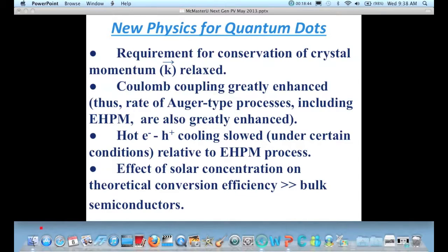And for the case of extracting them, which I won't talk about, but this is where we started looking at this, these are the so-called hot carrier solar cells. The efficiency calculated using the Shockley-Queisser approach, but assuming that the electrons don't relax or cool by phonon emission, but are extracted faster than the phonons and electrons can interact, can produce efficiencies above 65%. So you more than double the Shockley-Queisser limit with a hot electron or a hot carrier solar cell. And so there is work continuing in this area, and there's been some progress.